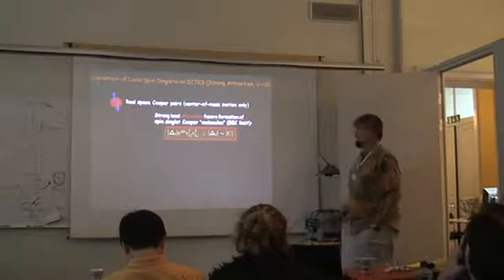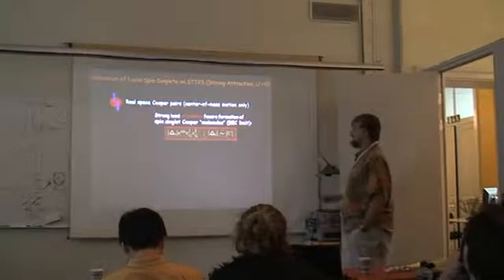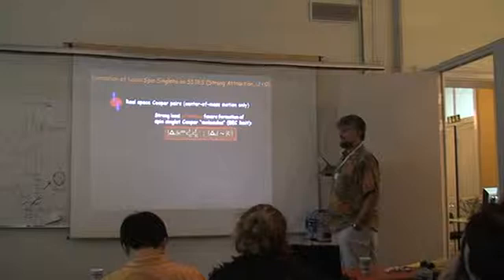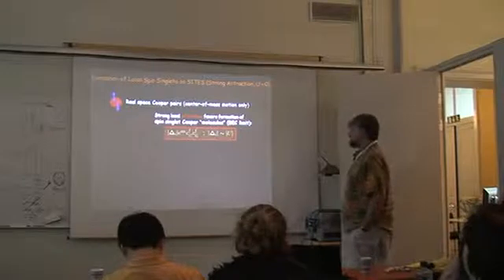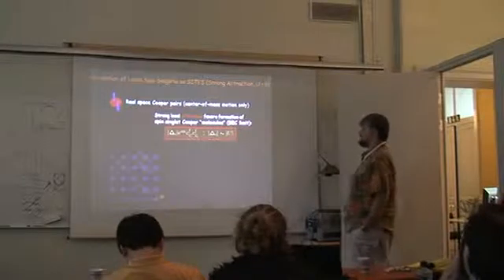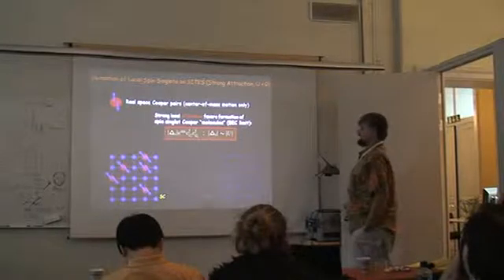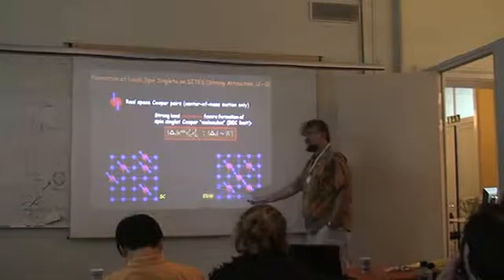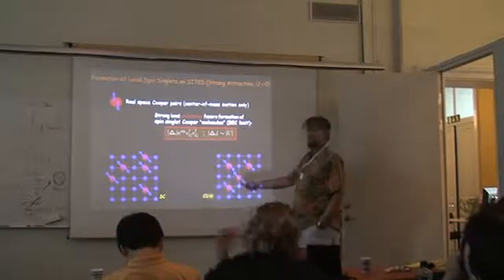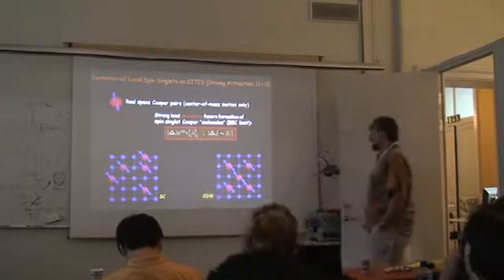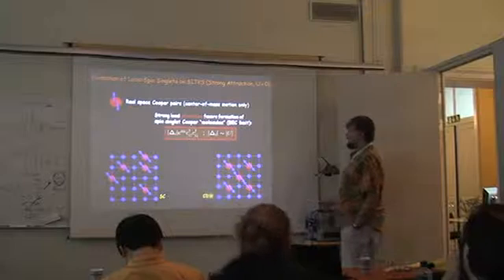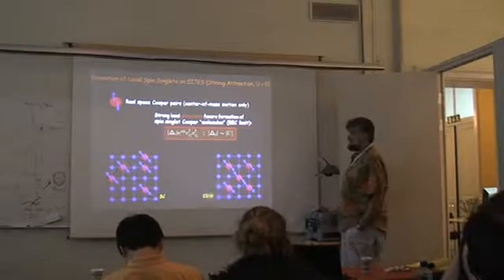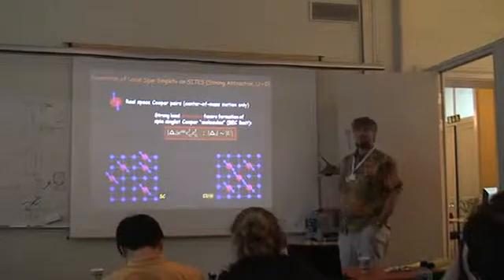When we have that, then we basically have a BEC limit. We have little Cooper molecules with electrons spin up and down sitting on the same site. And then, of course, on the lattice, we can solve this problem. And the solution looks like this. We either have a superconductor, where these Cooper pairs are floating around on the lattice, or they get locked into a charge density wave of Cooper pairs, sometimes called a pair density wave.